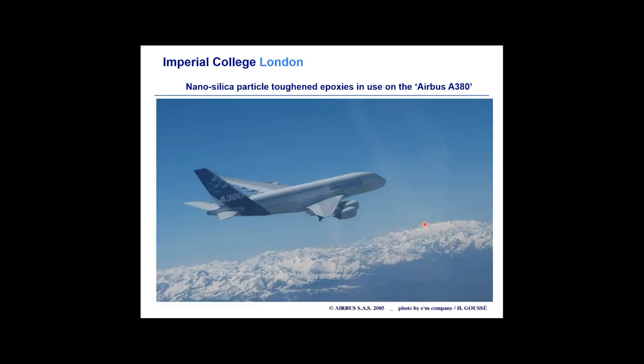This type of adhesive found very quick application on the Airbus A380. The vertical stabilizer here is CFRP, and it was found that they were getting erosion of the CFRP, and therefore what they did was to apply a coating of this nano glass toughened epoxy, and it gave them excellent toughness and erosion resistance on the tailplane of the A380.